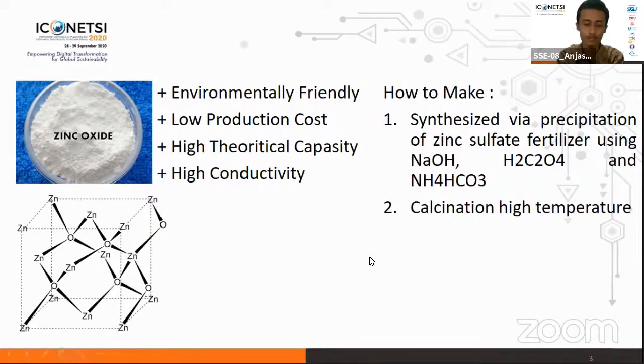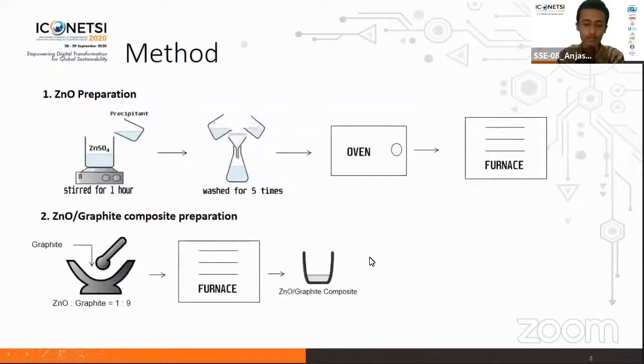Synthesizing ZnO powder by precipitation. In the study, zinc oxide powder was synthesized via precipitation of zinc sulfate fertilizer using sodium hydroxide, oxalic acid, and ammonium bicarbonate.